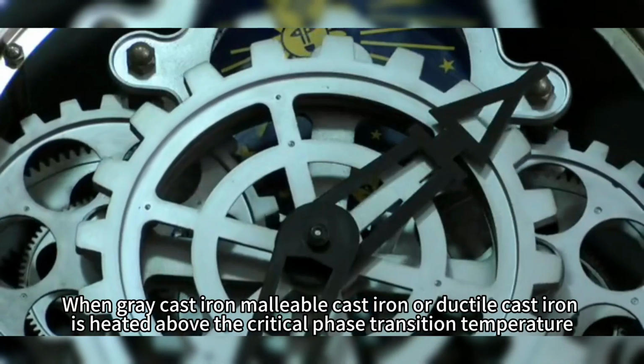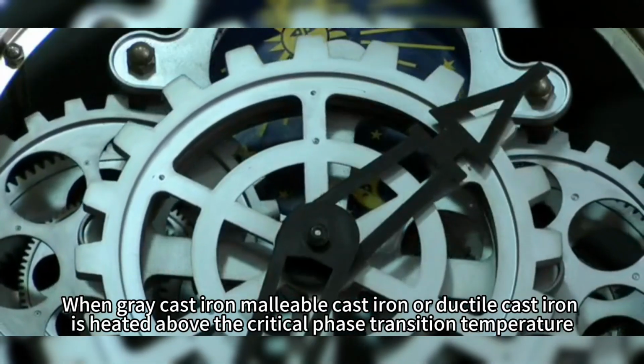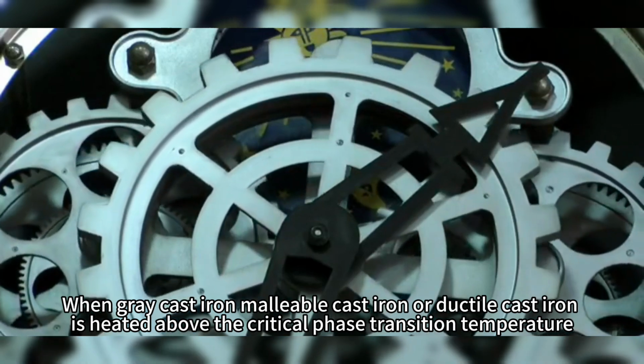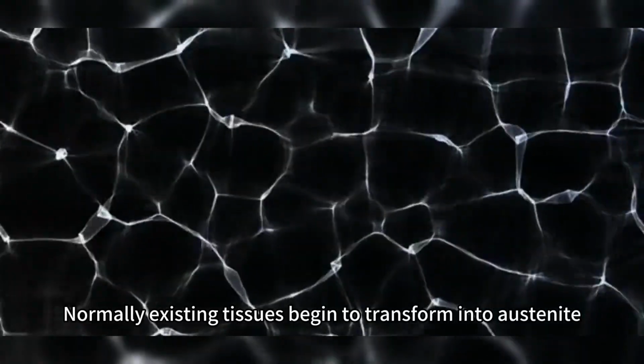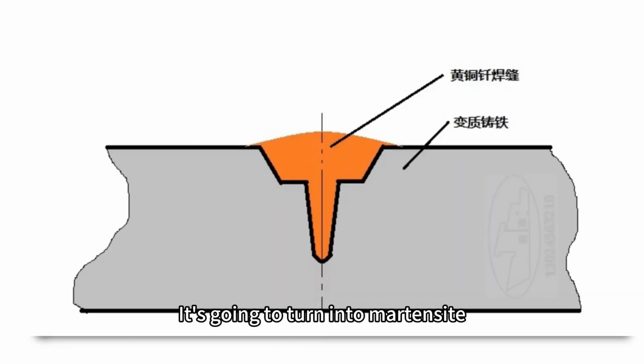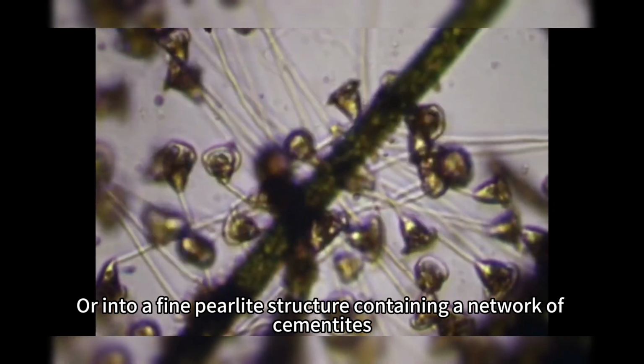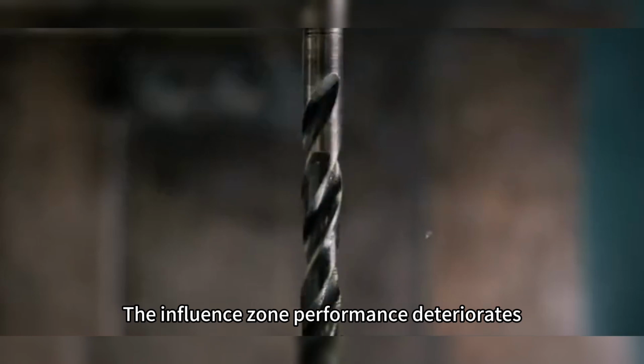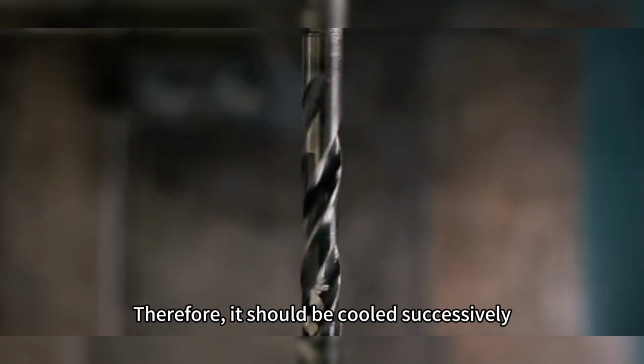When gray cast iron, malleable cast iron, or ductile cast iron is heated above the critical phase transition temperature, the existing tissues begin to transform into austenite. If the cooling rate is too fast, it will turn into martensite, or into a fine pearlite structure containing a network of cementite. The influence zone performance deteriorates. Therefore, it should be cooled slowly.